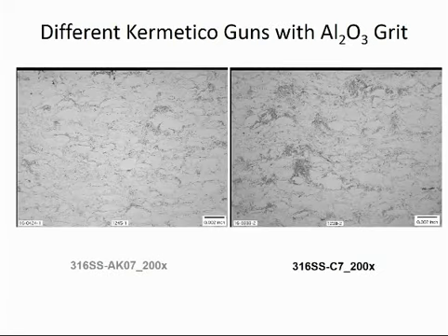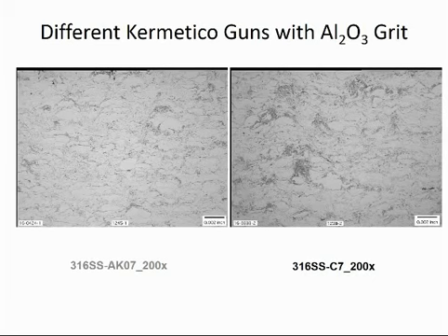Here we have an example of the difference of coatings applied by our standard AK07 standard HVAF coating, and the same material applied by our convertible gun, the C7, with added oxygen. You can look at this, and yeah, there's aluminum oxide in there, same amount in both, but clearly the C gun is creating more oxidation, because there's more oxygen involved.